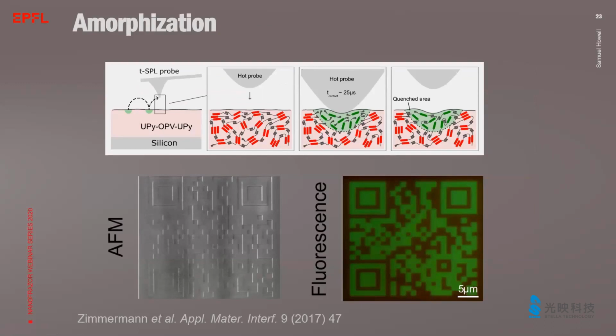We did local quenching of organic material. We used, for this case, a supramolecular polymer, which is a polymer where the monomer units are not linked by a covalent bond, but by hydrogen interactions. In this work, we explored this supramolecular polymer by TSPL and found that the fast cooling rates with TSPL allow processes which are not possible at the macro scale.